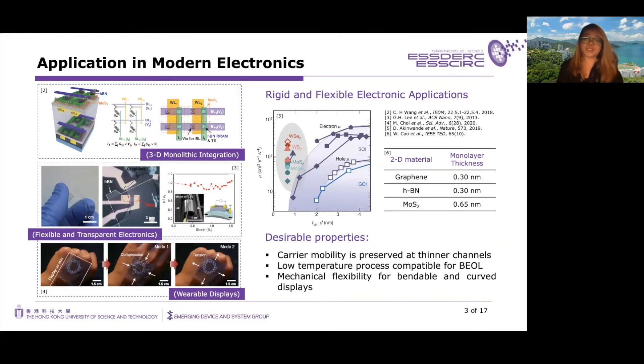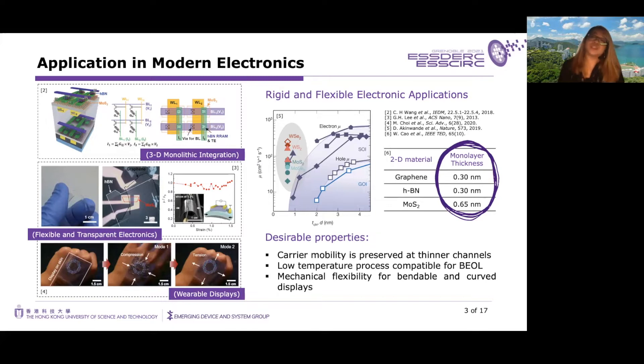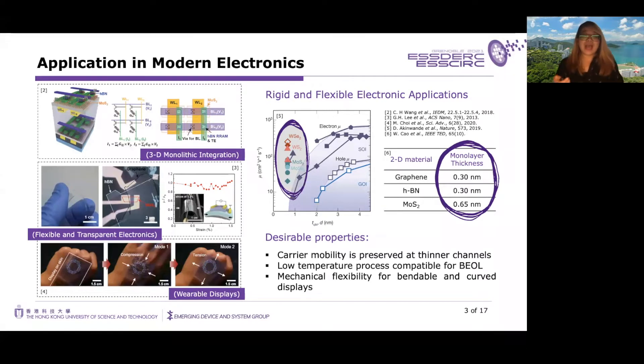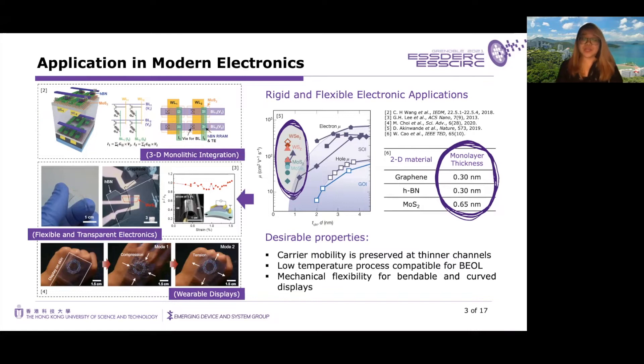To put some numbers into perspective, here are the thicknesses of different 2D materials in their monolayer form. Compared with traditional silicon-based technologies, the carrier mobility of semiconducting 2D materials including MoS2 is preserved at its atomically thin channel. This is why 2D materials are also considered to overcome the scaling limit of traditional transistors. Furthermore, as it is possible to transfer these materials at low temperature, fabricating active devices at the back end of the line and building heterostructures made of all 2D materials are greatly augmented.